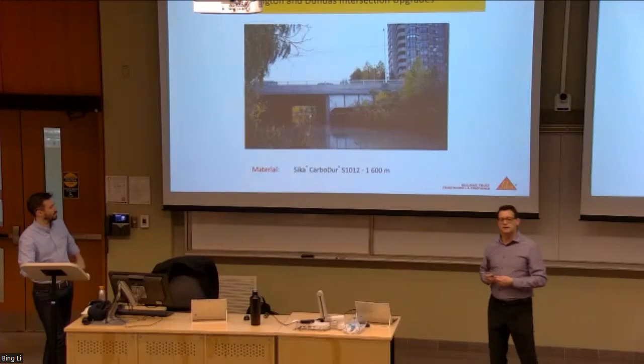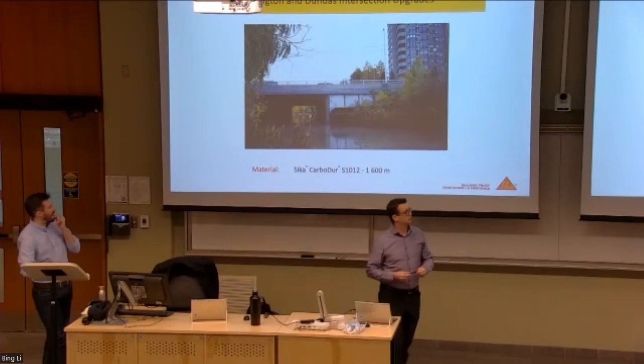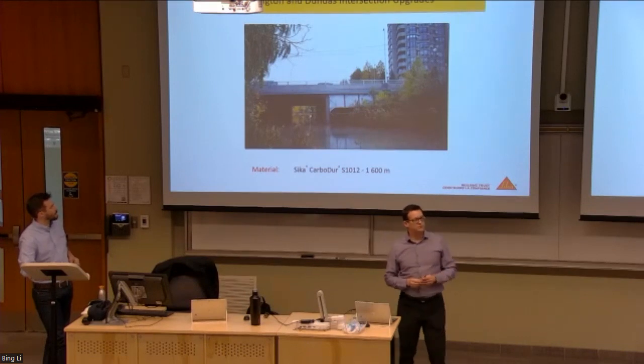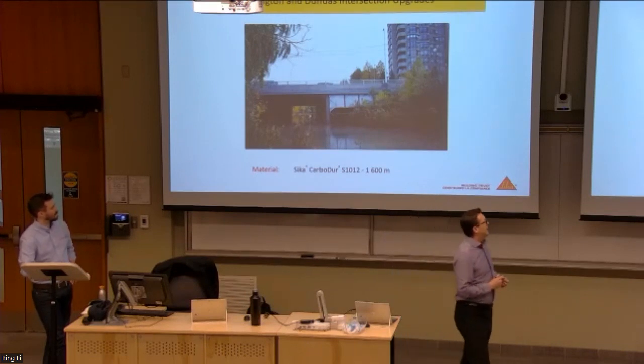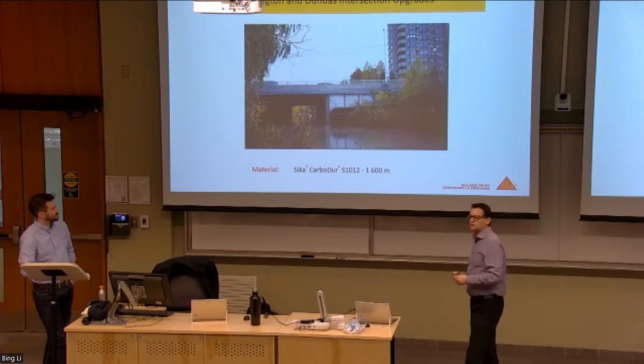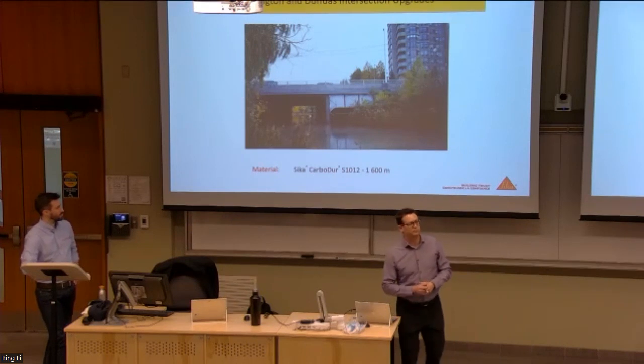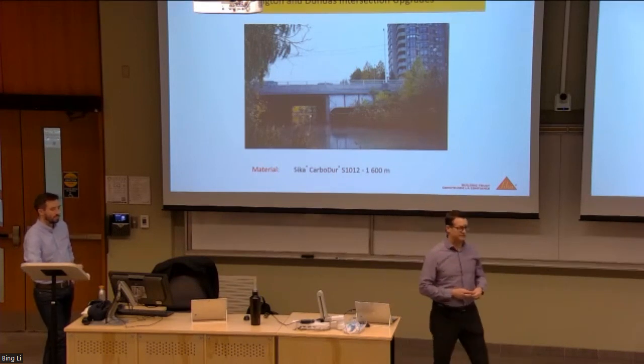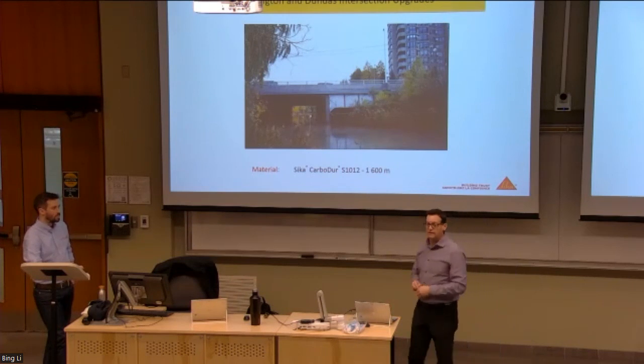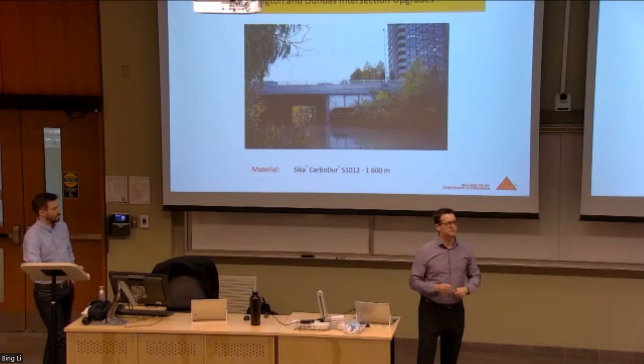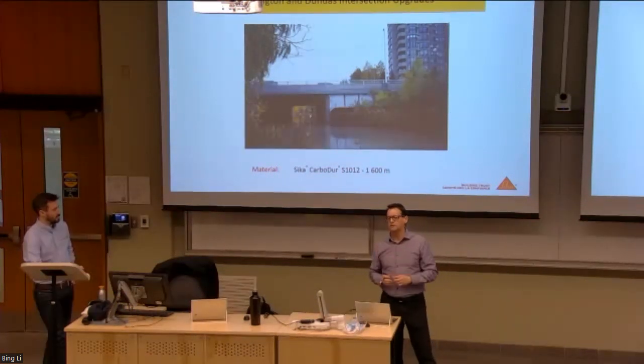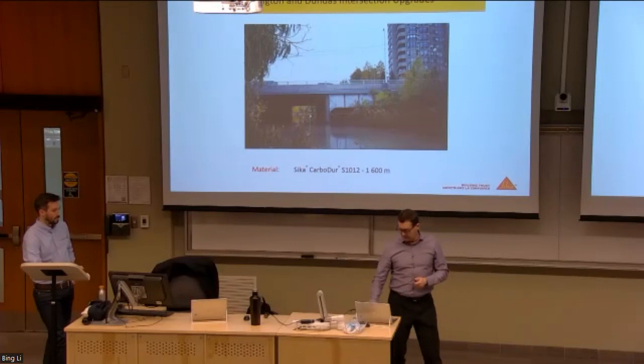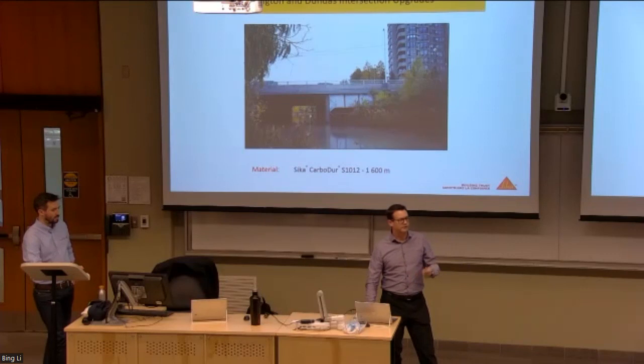Okay, so this is for Torontonians. This is the Islington and Dundas Bridge over the Etobicoke Creek. That structure underwent some lane expansion, and as I mentioned earlier with the graphic, with increased traffic loads over many years, this bridge was starting to show some fatigue after 50 years of service. There were a number of cracks in the concrete on the underside, so those were injected to structurally stitch the cracks and stitch that concrete back together. Then on the underside, we did 1,600 lineal meters of installation, again to stiffen and reinforce the underside of the bridge to structurally upgrade it.